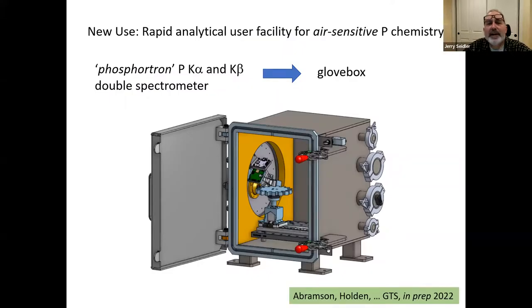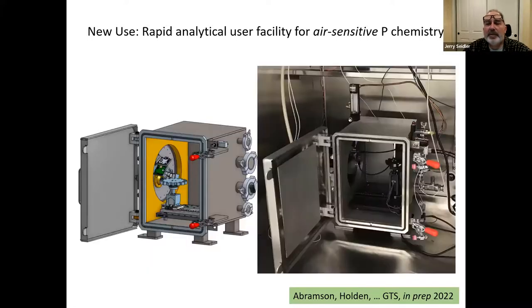Last couple things, we've just finished commissioning this instrument, which is a small double spectrometer that simultaneously measures phosphorus K alpha and K beta. And this is our first instrument that lives inside a glove box to measure air sensitive samples. And you can see here it's installed. The double spectrometer, the little pieces are right here. The X-ray tube is coming in from the back. You can see the black case of the X-ray tube and the samples on this wheel. The sample wheel would get pushed forward when it's time to actually take data.